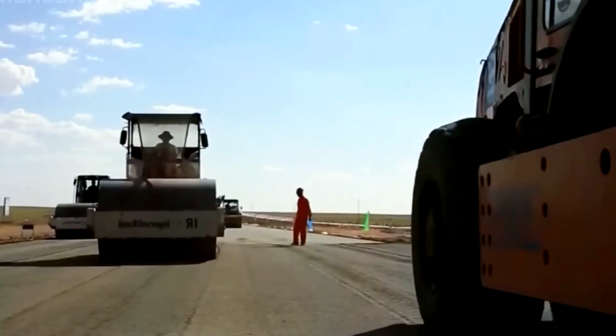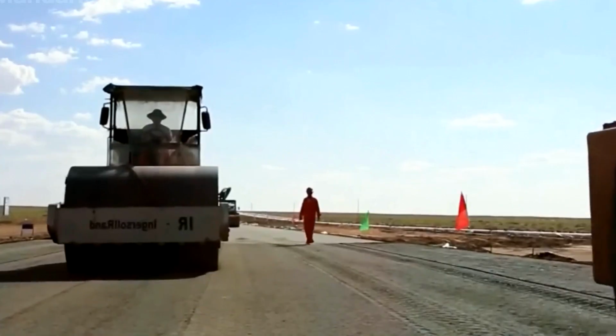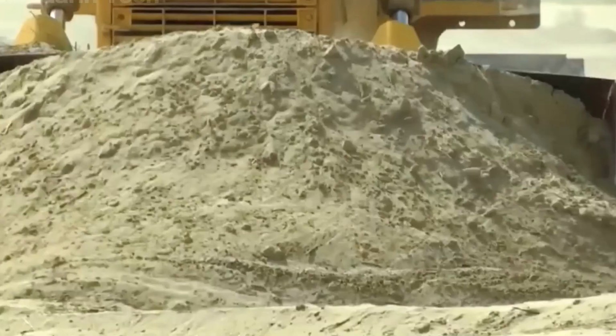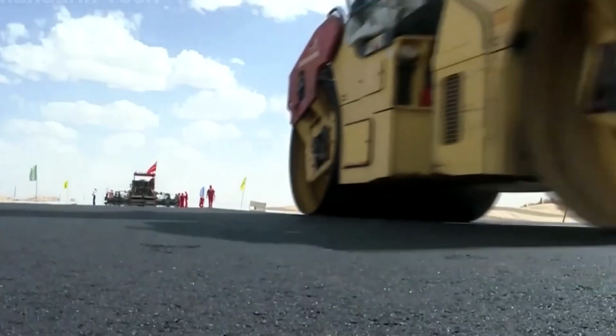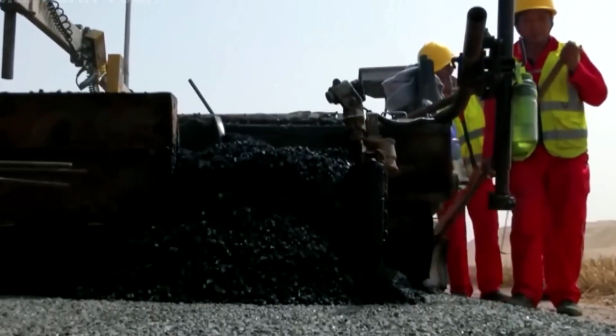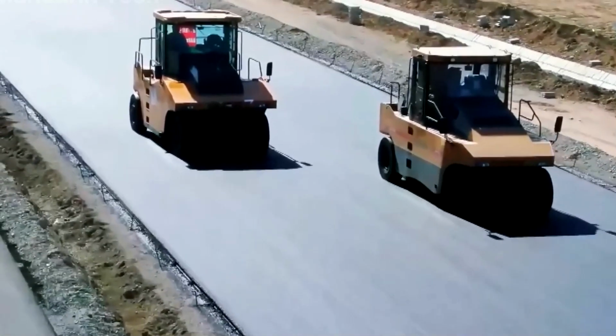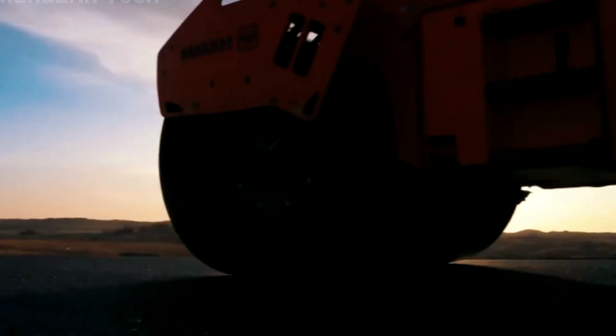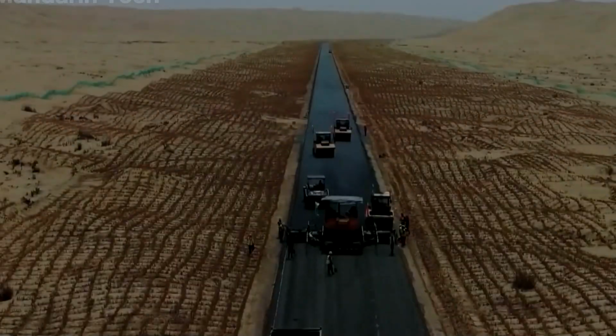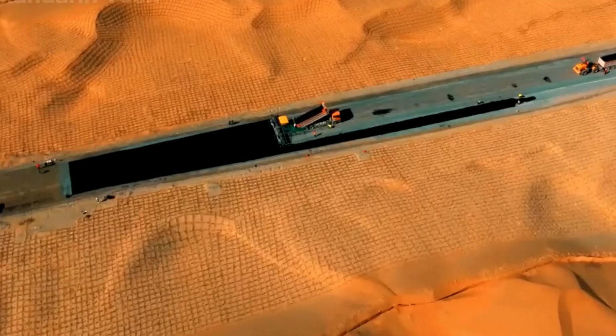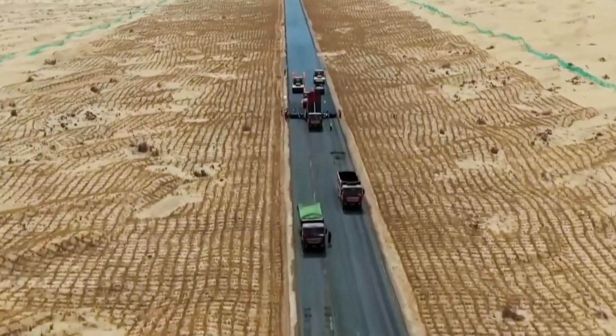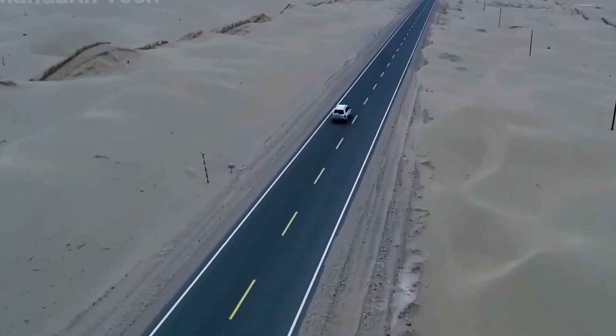The first passes use heavy steel drums for compression. The final ones switch to rubber tire rollers, which knead the surface to seal tiny air gaps and create a smoother texture. And this is not the limit. Thermal sensors on each paver track the surface temperature in real time. If the asphalt drops below 140 degrees Celsius, rolling stops immediately, otherwise cracks could form once it cools. Supervisors check flatness with laser beams, allowing no more than 3 millimeters of deviation per meter.